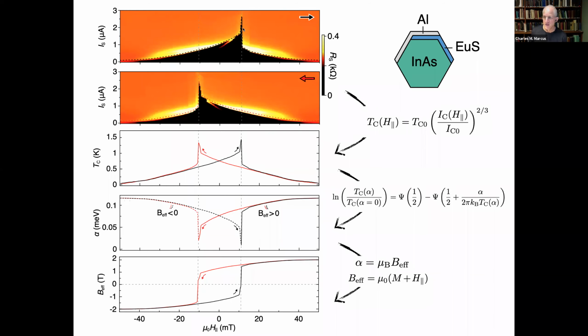And during that place where it's demagnetized, as long as any residual ferromagnetic domains are smaller than the coherence length, the superconductor doesn't see all of those disordered domains. It just sees zero magnetization. So it tells us two things. First of all, it tells us that the domain size is small compared to the coherence length, which is correct from what's known about europium sulfide. There was a study by Strambini and co-workers on the europium sulfide grain size that's consistent with this.